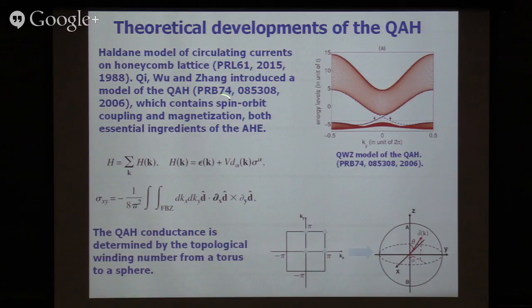In this kind of model, we later did some work on the quantum anomalous Hall effect based on spin-orbit coupled ferromagnetic material. Basically, you can describe this by a two-band model, and any two-band model can be expanded by Pauli matrices with a three-vector coefficient. The Hall effect of this insulating material is exactly what is called a Skyrmion map, in momentum space. So it's basically a mapping from the momentum space, which forms a torus, to the vectorial direction of a three-dimensional vector, which is the surface of the sphere. When you make this mapping, it's a topological invariant, classified by an integer, which is exactly a quantum Hall effect without any external magnetic field. You don't need any Landau levels to have quantum Hall effect. But due to the ferromagnetic moment of the material in this insulator, you can actually have a finite